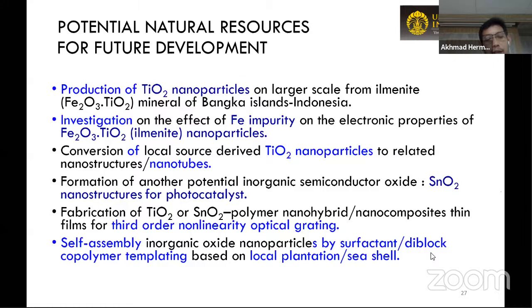Another thing is related to the synthesis of nanohybrids or nanocomposites. In my previous work during my PhD at NUS, TiO2 combined with the polymer polymethyl methacrylate, as a nanocomposite thin film, could show third order nonlinearity with a very high Chi3 value. This can be achieved when the inorganic nanostructure material is encapsulated by the polymer matrix.